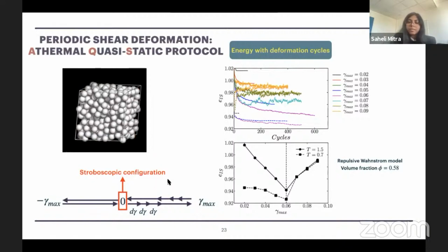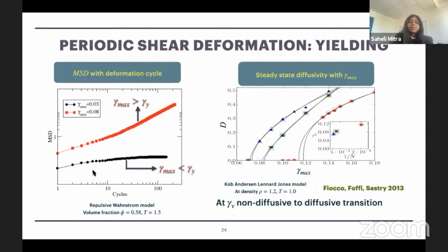We can also track the movement of the particles from one cycle to the next and compute their mean square displacement. So for example, if we plot their mean square displacement with the deformation cycle, we will see for shear amplitudes below yielding, this mean square displacement becomes a constant. That means in this regime, from one cycle to the next, there is no net displacement of the system. So the particles do rearrange during the deformation cycle, but they come back to their initial positions in the steady state.